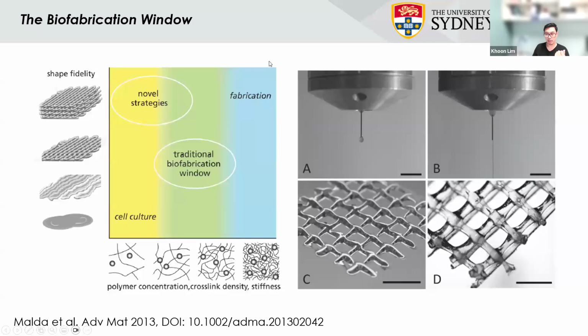When you think about bioprinting, this is a seminal paper that was put out by Jos Malda's group in 2013. At that time, when we were working on extrusion-based bioprinting, what we do know is that the printing is only advantageous if you can get a specific shape out of it. Everyone knows that you can mix hydrogel precursors, pipette them, and crosslink them. That is quite simple. If it's such a simple process, why do we need to complicate it with bioprinting? Unless bioprinting is going to offer us some specific advantages. In this case, bioprinting is supposed to give you a construct that is identical to what you would have designed. So shape fidelity and maintenance of the shape fidelity is really important.